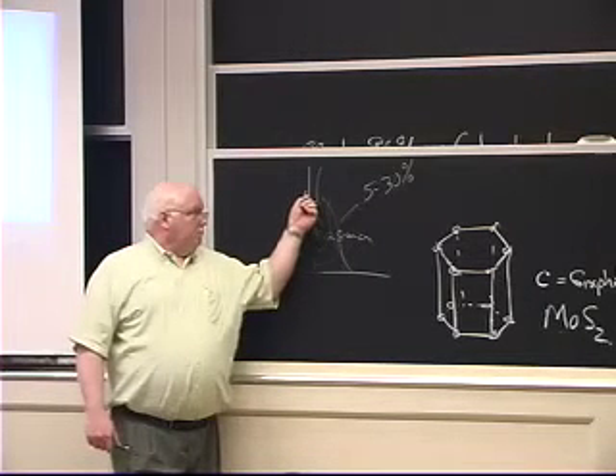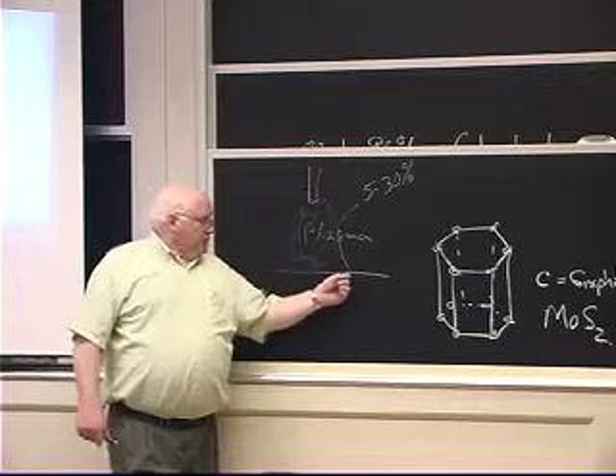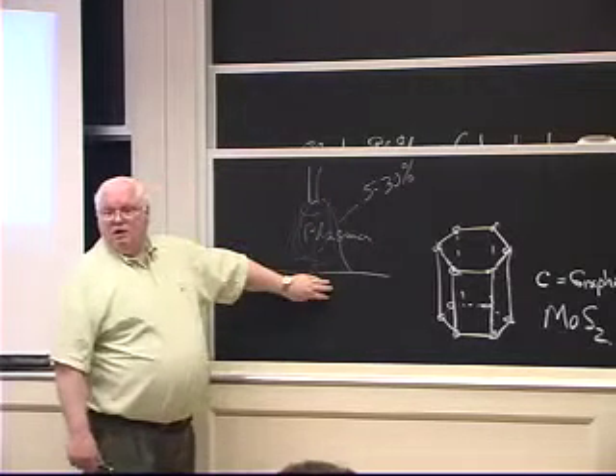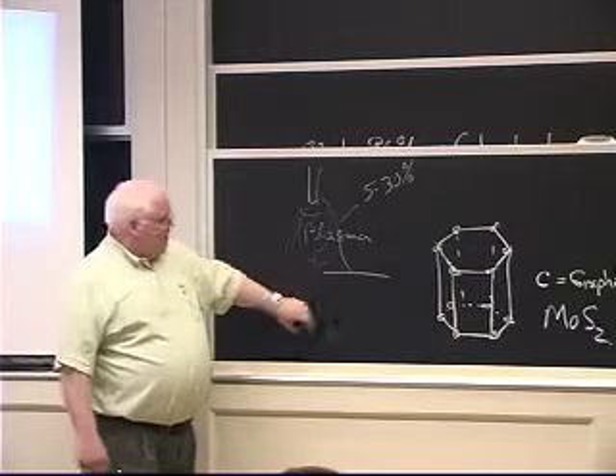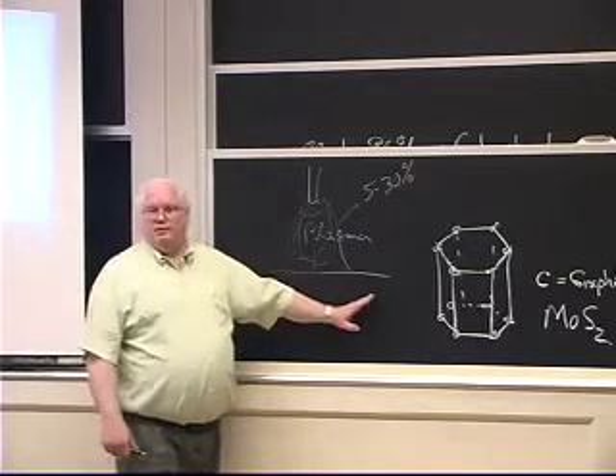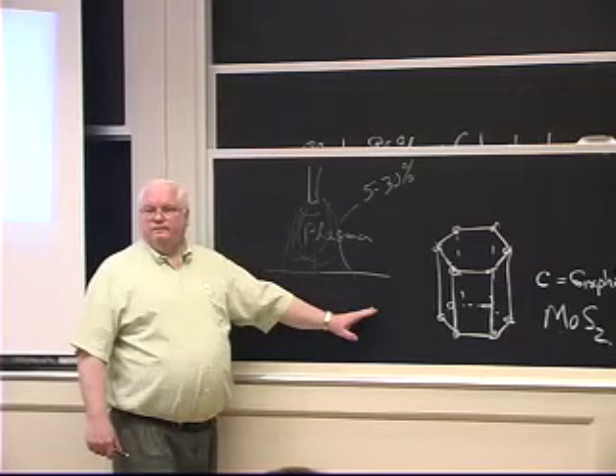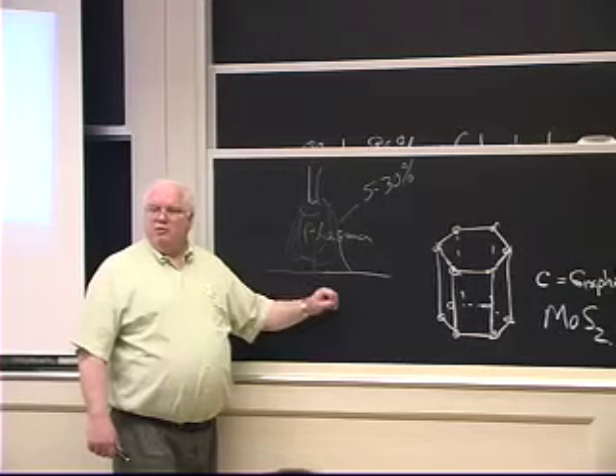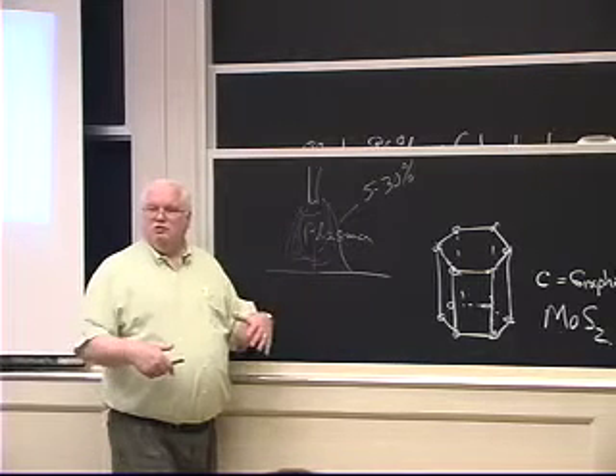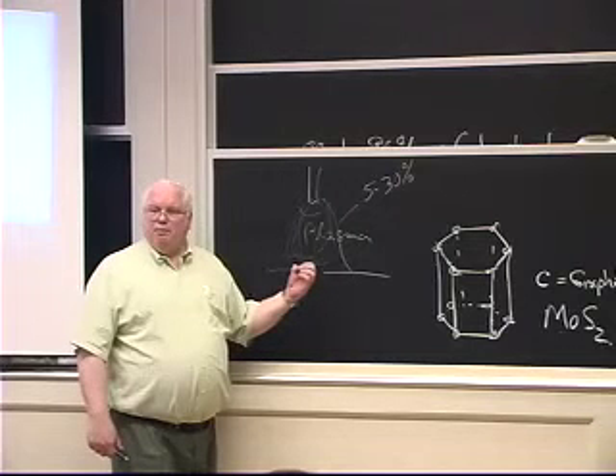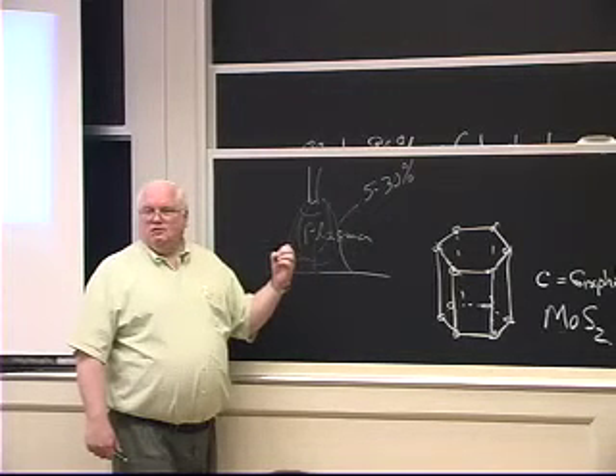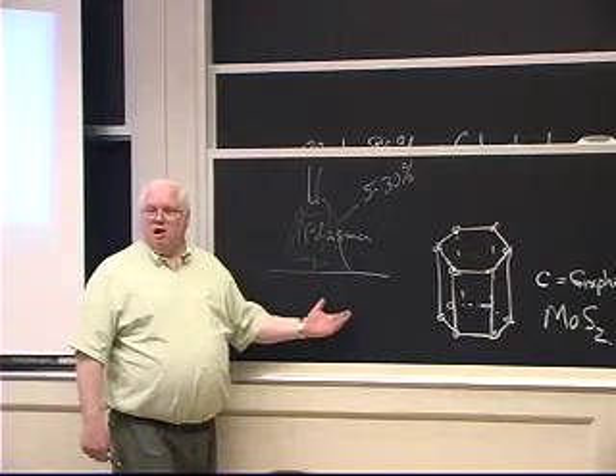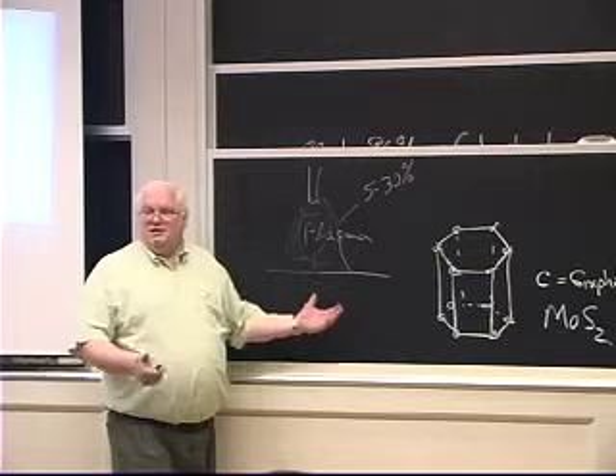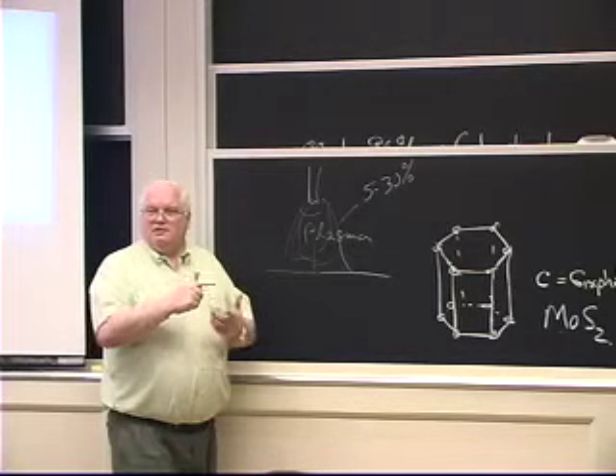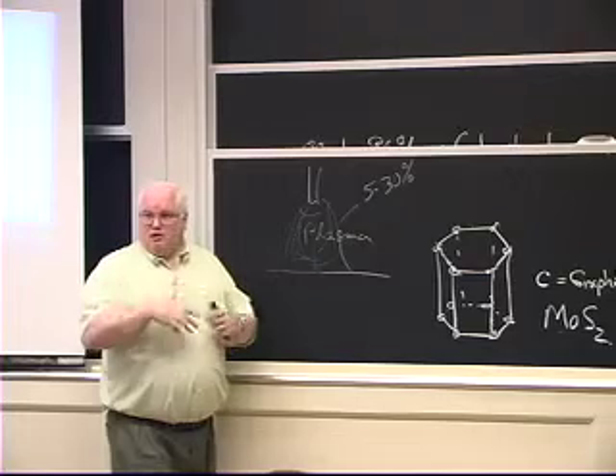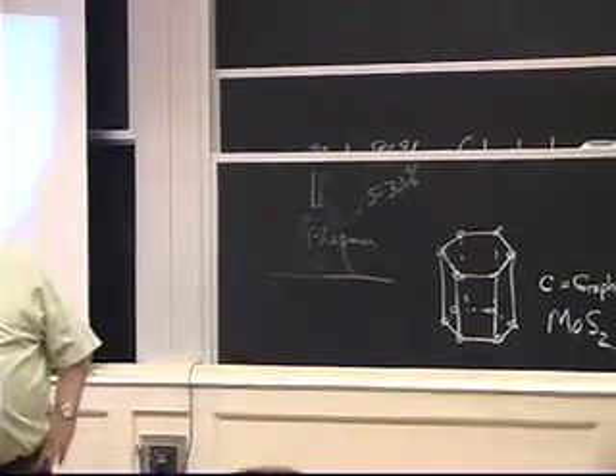We now have gotten to the point where we can model a little bit about what goes on as it interacts with the surface. We've gotten to the point where, with completely different models, we can model the convection in the weld pool. We might talk about that in the next few days. We've always been able, for 30 or 40 years, to model the heat flow that goes on. We do not have computers big enough, and probably will not for another 50 years, to model the residual stresses as this thing cools down, the elastic plastic, because that's a coupled thermomechanical process with nonlinear properties of the materials and temperature-dependent properties of the materials. And you start talking about transient, thermomechanical, nonlinear, all these things that the mathematicians over here would love to come and start talking about how we can improve our modeling techniques. So can you model the welding process?